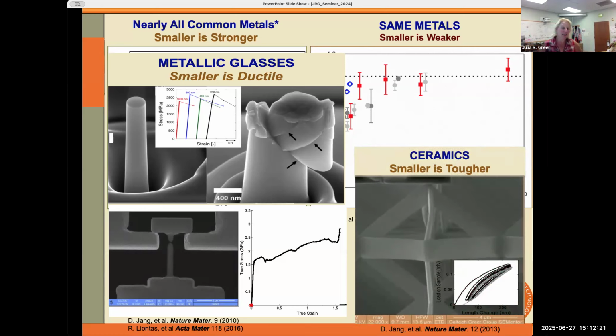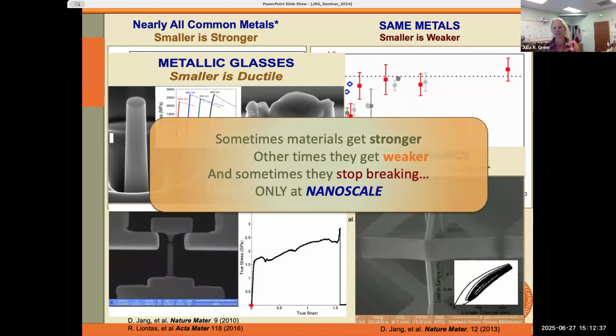And if you were to calculate the tensile stress component within that beam, it's 1.7 gigapascals. So ceramics are not supposed to stay intact when they're being tensed with that much stress. So what this is teaching us is that sometimes materials can get stronger, some other times they can get weaker, some other times you can suppress brittle failure. But all of these phenomena occur only at the nanoscale.